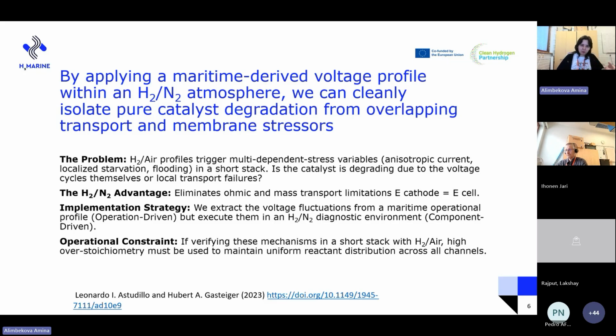Then if we use the voltage transients from some maritime drive cycle onto a hydrogen-nitrogen environment, we're basically combining this component-driven AST strategy to isolate the influence of the maritime profile with the operation-driven maritime profile. Then we can map exactly how the maritime voltage swings affect the state of health of the catalyst, how they drive platinum dissolution, or for example carbon support corrosion, completely independent of the water management issues and gas distribution problems.